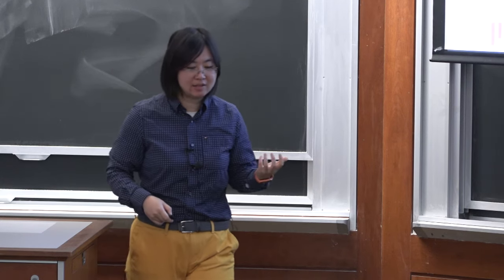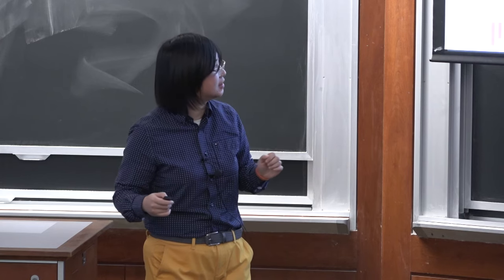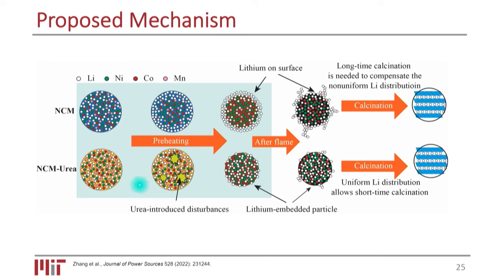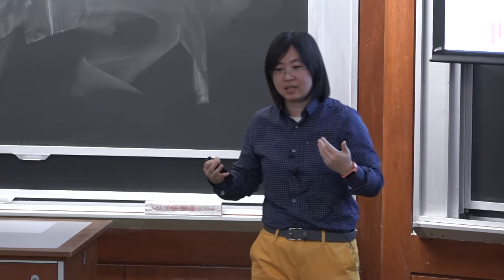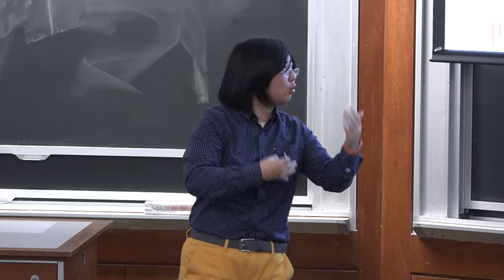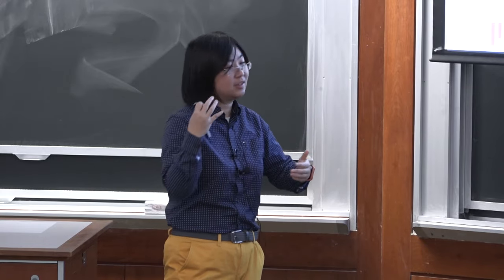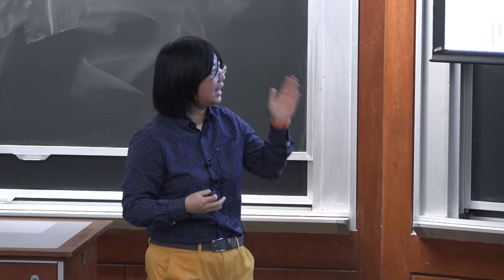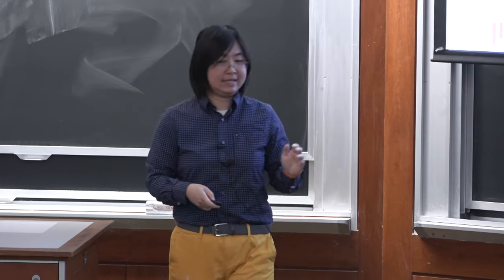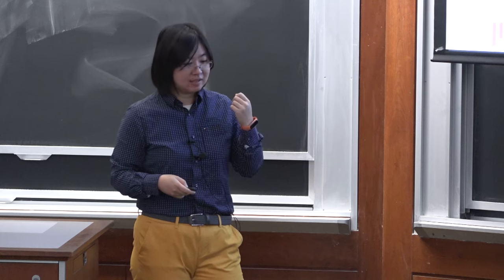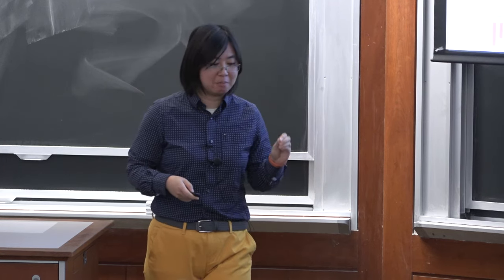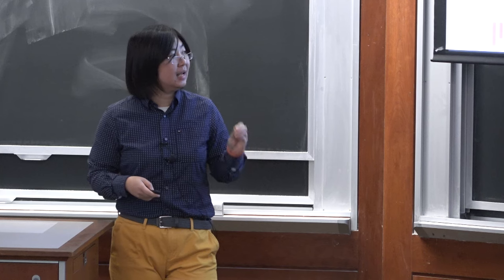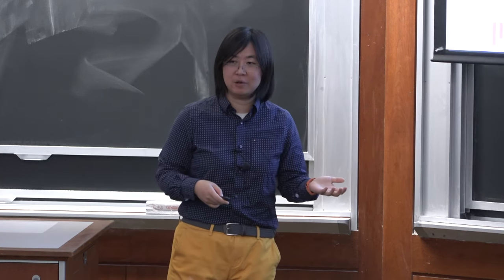So to summarize the mechanism using this schematic, by comparing these two, the urea would decompose. And when it decomposes, you also see from the video that it will generate bubbles and enhance the internal mixing inside the droplet such that we enhance the effective diffusivity inside the particles. We can have a more uniform distribution in the end materials. And that's the key reason why we can achieve much better mixing of the elements and then achieve the same level of performance in the batteries.